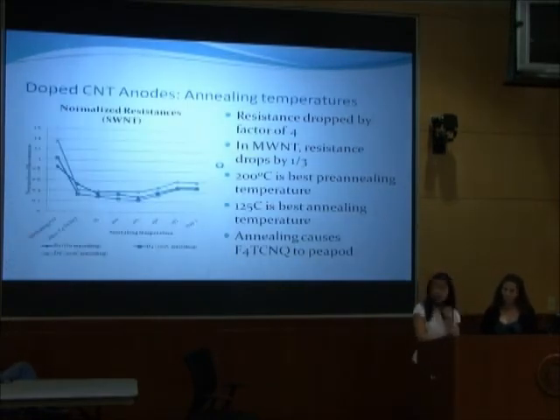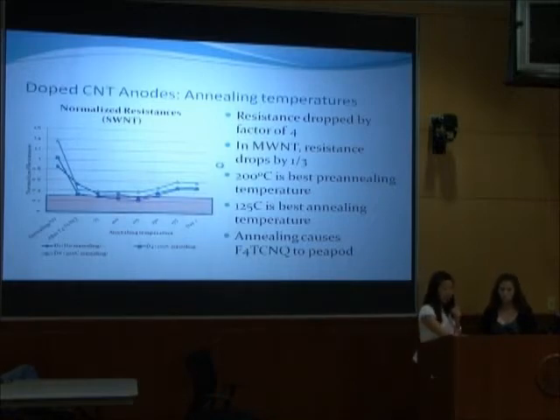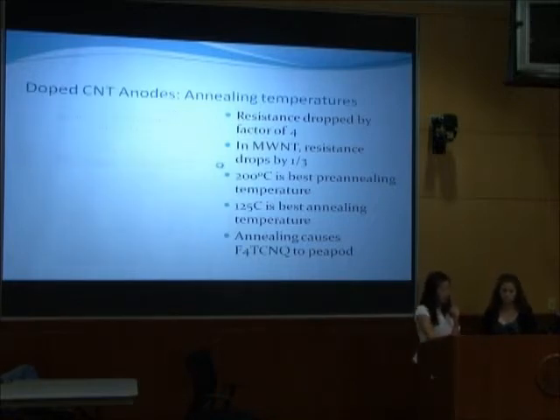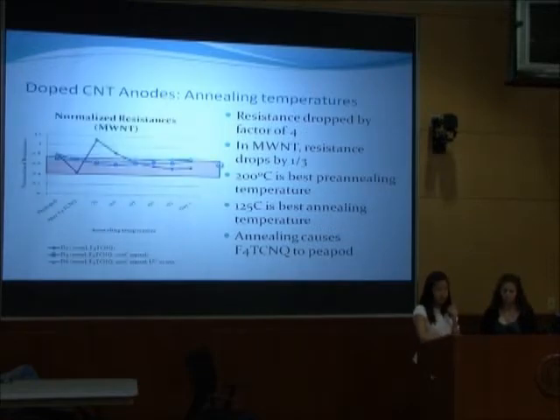These were the normalized resistance for our single-wall nanotubes. Normalized resistance is simply the resistance we measured after doping divided by the resistance we found before doping. We discovered a strong doping effect on the single-wall nanotubes. The resistance dropped by a factor of 4. In multi-wall nanotubes, the resistance dropped by up to 1/3, which is still a significant improvement in resistance.